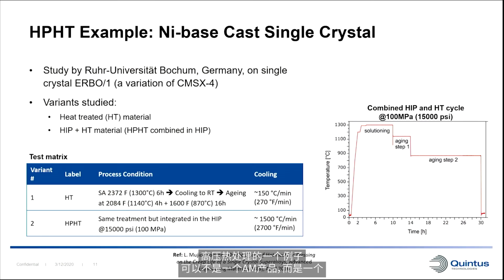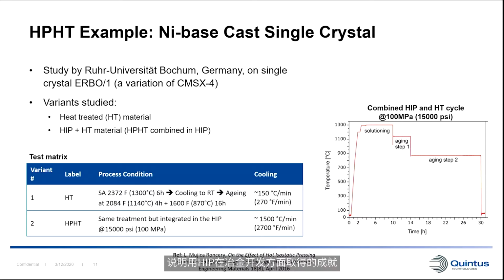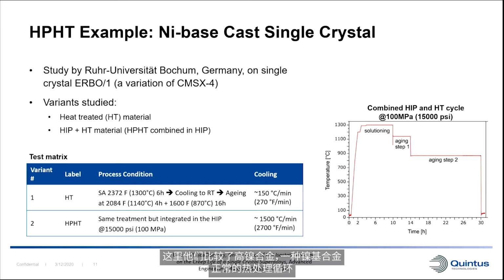An example of high pressure heat treatment could be, not an AM product, but a single crystal turbine blade, where some work's been done at the University of Bochum in Germany, which is really excellent work and a good example of what can be achieved in terms of metallurgical development using the HIP. Here they've compared a normal heat treatment cycle for a high-end nickel-based superalloy with high-pressure heat treatment using a Quintus HIP with a combined cycle.